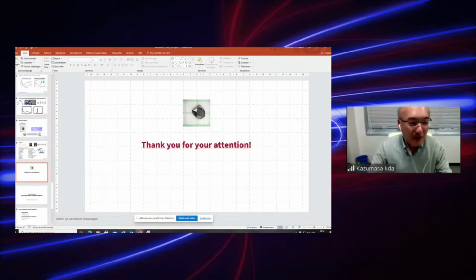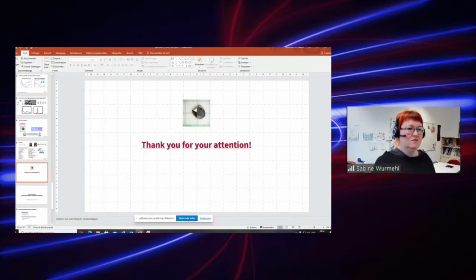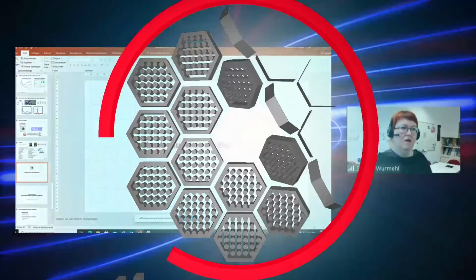I have a question. When you add cobalt to the materials, is there any size difference between the pure materials and the cobalt samples? Yes, so you see a very small difference in the lattice parameters. Iron and cobalt have very similar ionic radii, so this is tricky, but we can really probe the composition and the structure.